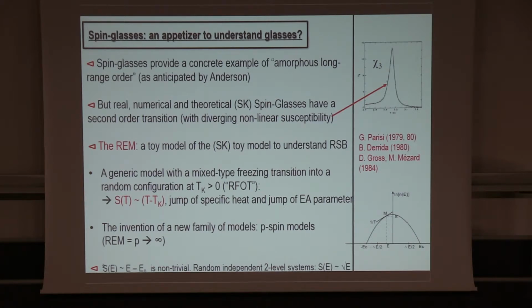Because by definition, the random energy model has no structure. You freeze into something that's random by construction. The entropy goes to 0 linearly as the temperature goes to Tk, this Kauzmann temperature, with a jump of specific heat and a jump in the Edwards-Anderson parameter, that is the degree of freezing, if you want.